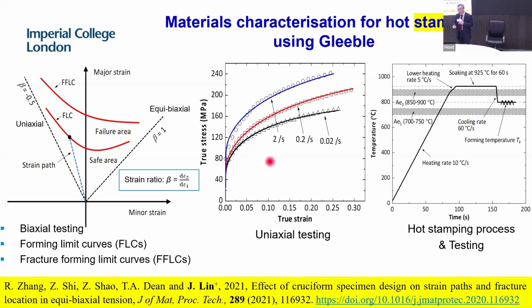And what we need to do as a basic test is a uniaxial tensile test. We need to generate data. We know the properties, then we can do the simulations. And then another data we need to generate is the forming limit, because it's a sheet metal. We say this is the minor strain, and the vertical axis is the major strain. For the forming limit curve, if above this, that's failure, below this, that's safe. We need to do similar tests to generate the data for these.